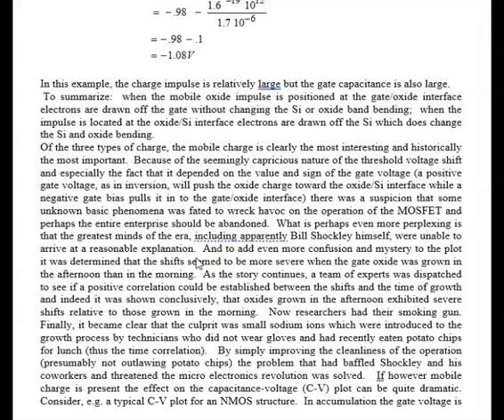So here's another little fact. It seemed to work out that it was even more mysterious, that it depended on the time when the gate oxide was grown. And we'll talk about growing of gate oxides in just a little bit. It worked out that if the gate oxide was grown in the morning, the results were reasonably good. If it was grown in the afternoon, the results were terrible, specifically if it was grown after lunch. How could that be? That is completely inexplicable.